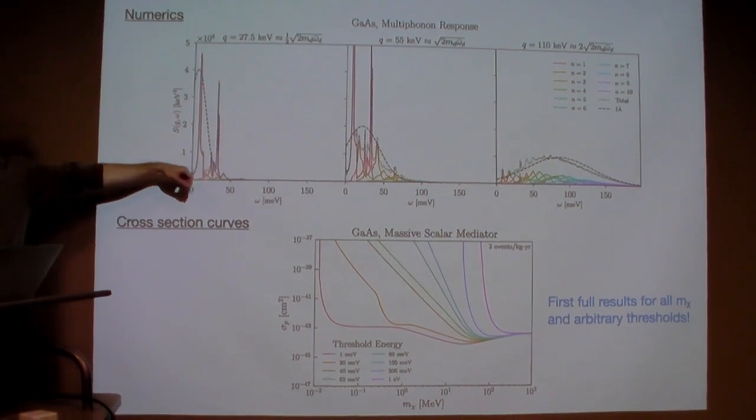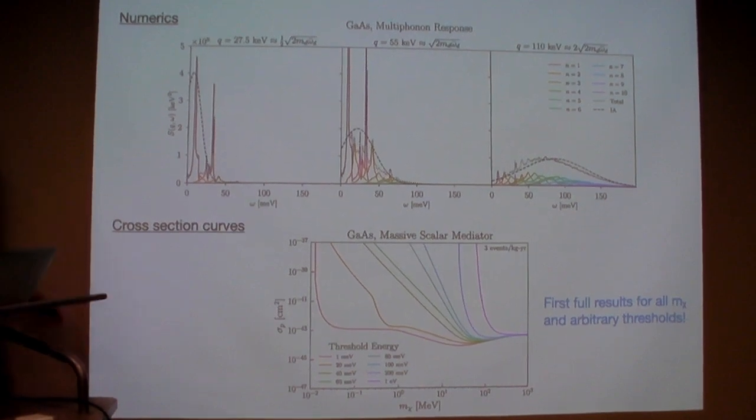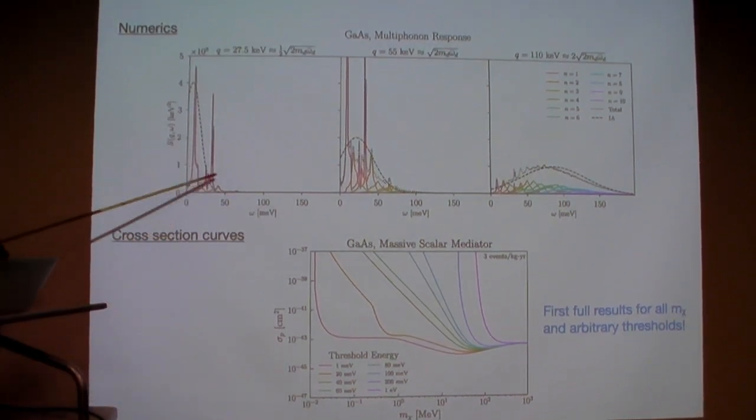Yeah, well, this entire formula and all these things, this is all reproduced in neutron scattering data. Of course, that's a different kinematic regime than what we're looking at. But the way they measure the density of states is literally by scattering neutrons, measuring these peaks, and then inferring the density of states. That's how this is measured. So yes, there is a lot of experimental backing for these things.